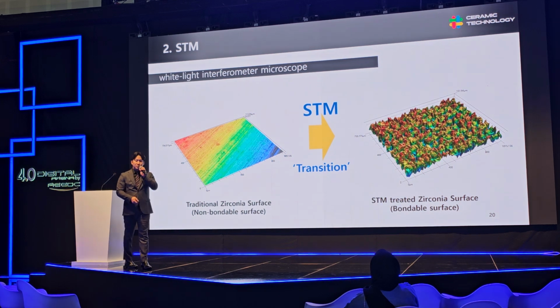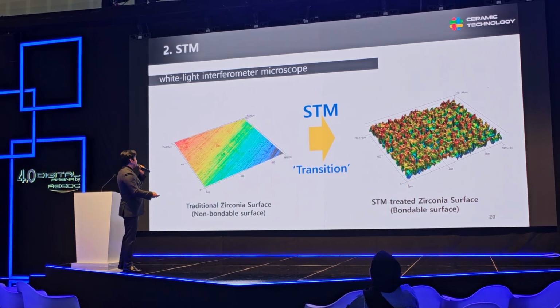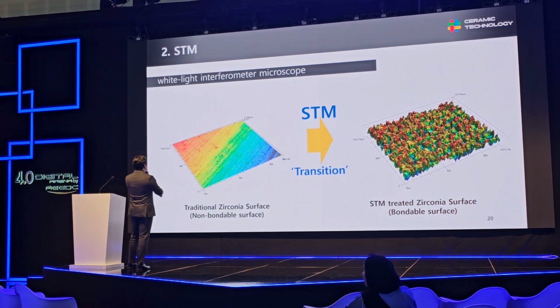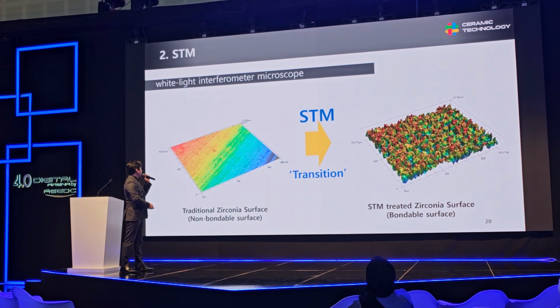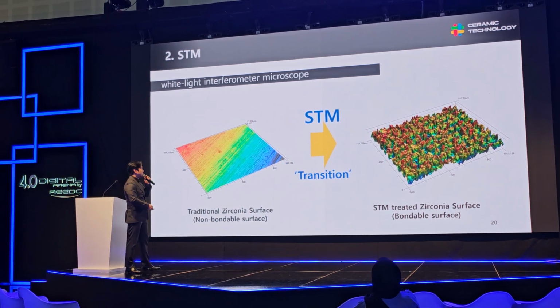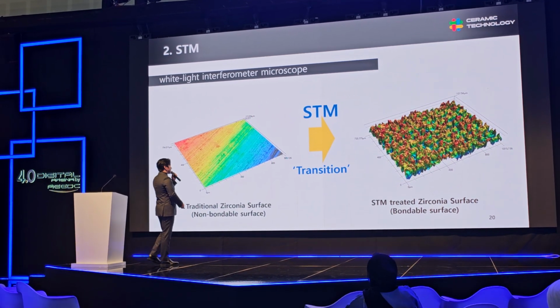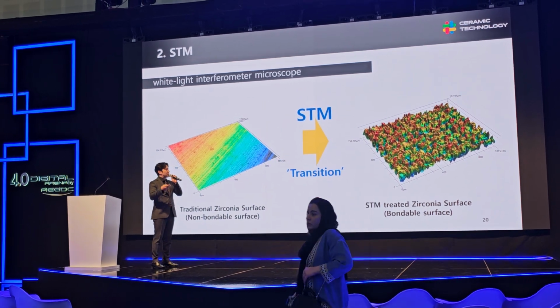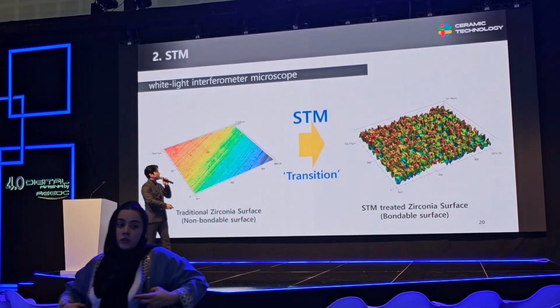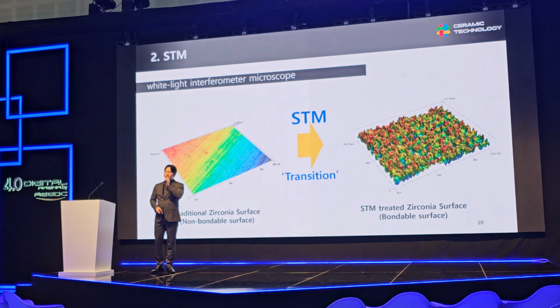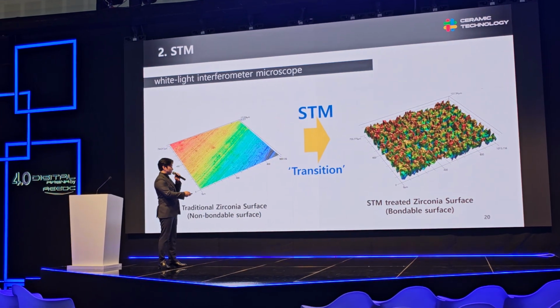So we prepared the 3D images for your understanding. As you can see, there are no undercut structures on the traditional zirconia surface. But after STM transition, the surface shape changes like this. So this is why we describe it as a transition occurring after this treatment.